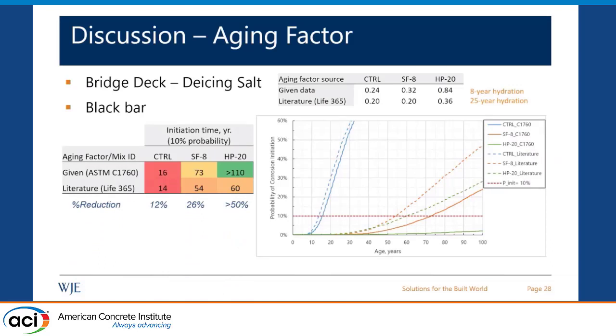The curve that you're looking at here is how the probability of corrosion initiation changes with time. And the values in the curves in solid lines are the ones with given input parameters for the session. The dotted line is when I revise the aging factor to be consistent with the assumptions presented in literature and in Life 365. And this table here provides a comparison of the two.